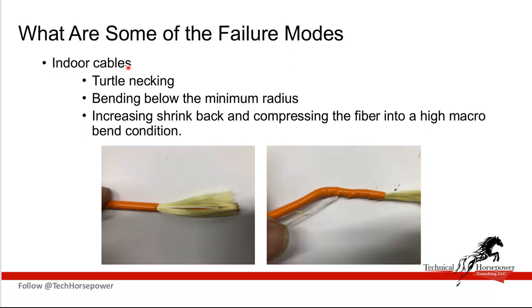So what do we call this? We call this turtlenecking. We also have bending below the minimum radius. When you're pulling it, you literally will pull almost a 90-degree bend. And you may actually exceed the minimum bend radius of the fiber, which also will shorten its life. You may not break the fiber, but you may shorten its life quite a bit. The same is true with increasing shrink back by compressing the fiber into this high macro bend condition. It's not always a good choice.